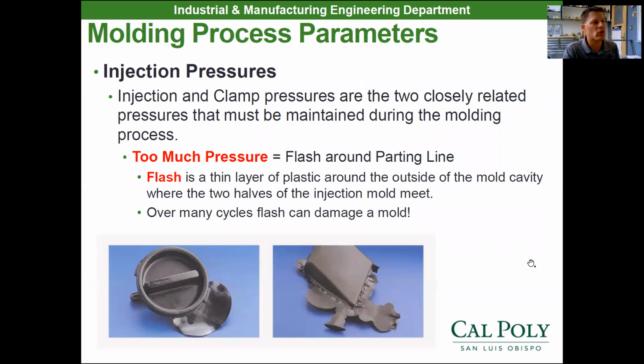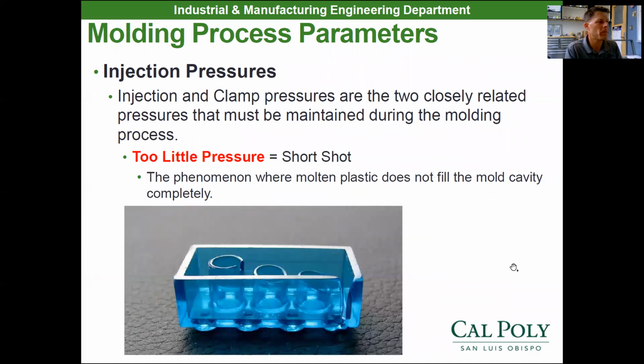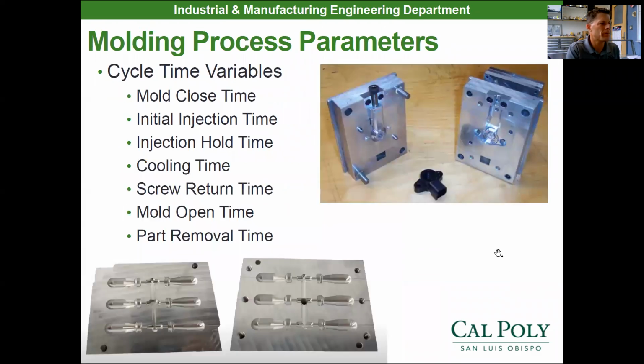That's why you really want to control your injection pressures, and we use math to figure out our injection pressure. We don't just kind of guess. We use simple math, like I explained before, with the pressures and the cross-sectional area of where we're at in our parting line. Now, if we just crank it down and didn't give it enough pressure, we get what we call a short shot. So that's where the plastic doesn't actually fill the mold cavity completely, and we end up with an unfilled part, an unsellable part, or an unusable part. So that's too little pressure.